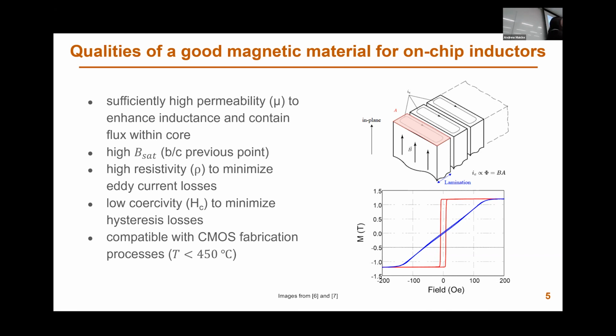I'll talk a little more about losses. So in power, we care about two particular contributions to core loss. One is eddy currents, and eddy currents just come from Faraday's law. Whenever you throw flux into a material, you generate a voltage to oppose it because of Faraday's law, and that voltage causes eddy currents to circulate within the material. And these currents are usually really bad because they don't actually deliver power. They just sort of exist in the material and dissipate as heat. So actually for core materials, you don't want anything that's really conductive. You want something that has very high resistivity.